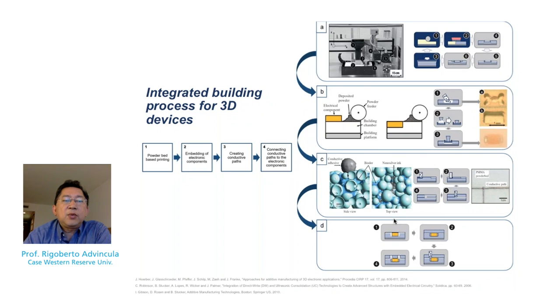So perhaps one can start with a powder bed based printing, which creates the passive component, but at the same time one can embed the electronic component. You can either have both the passive powder and active embedded component delivered on the surface during printing, or one can use a first patterned powder bed based printing of the passive component and then bring this to another section of the printer or a designed 3D printing equipment, or actually place this on another printer and then create your embedded electronic component.